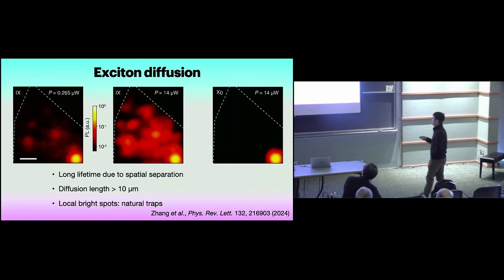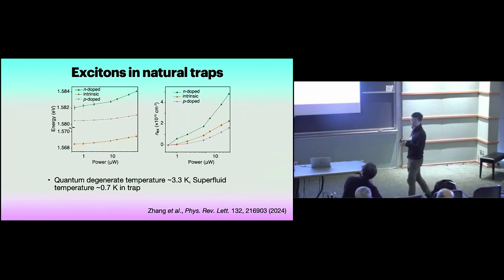Of course, we don't know exact nature of these cold traps now. We had some ideas, but we don't know for sure. These traps may be good for realizing condensate. So one thing we did is to look at the exciton density inside the trap and compare it with directly under the laser illumination. We find that inside the trap is actually not significantly lower. So that's another good thing. Because you have these natural traps, you can actually get pretty high density of excitons inside these traps. We find that the quantum degeneracy temperature is around 3 Kelvin. So it's still below our system temperature, but potentially we can realize much higher densities by designing traps or designing some mechanism we can shuffle excitons to these traps.